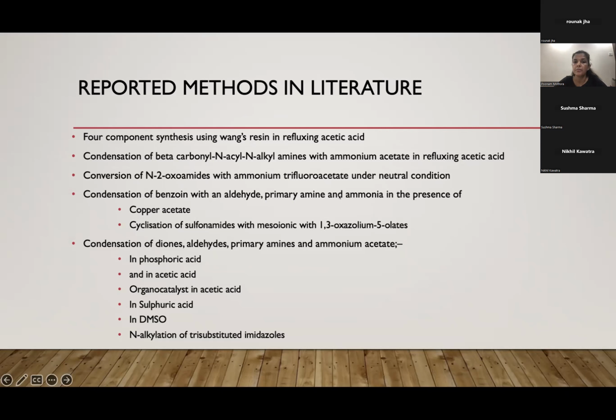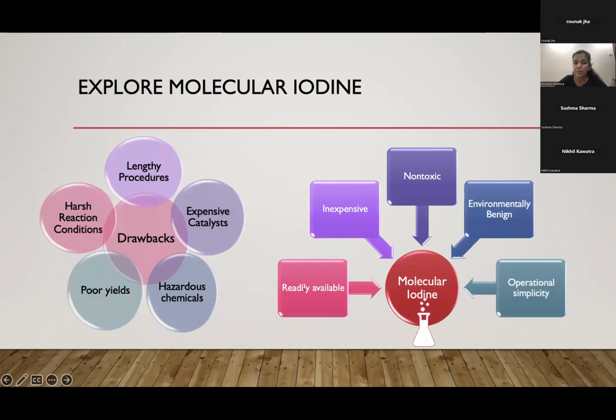We should look for alternative methods which are eco-friendly, where the catalysts are less hazardous, because the reported methods have poor yields, 40 to 90% yield of the product, even after 4 to 6 hours. So based on that, we explored the chemical properties of molecular iodine, which is inexpensive, non-toxic and readily available.